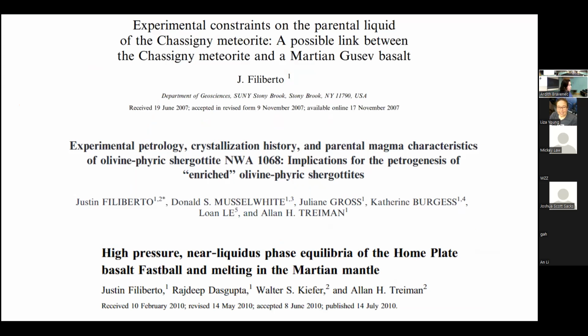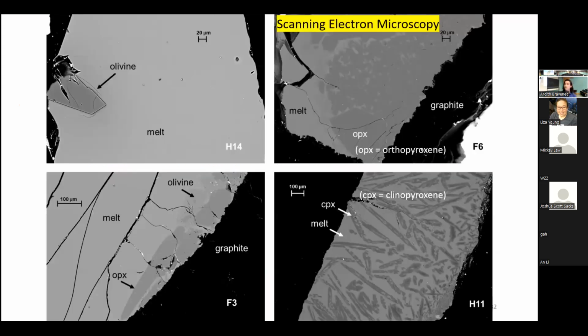Another very important thing about these samples is that they were run in graphite capsules, which you can see here on the SEM image, given that black surrounding the gray olivine crystals in melt. You'll also notice that the crystals are very large in terms of these kinds of experiments, perhaps. Some of them are even greater than 100 micron, so they're ideal for analysis.